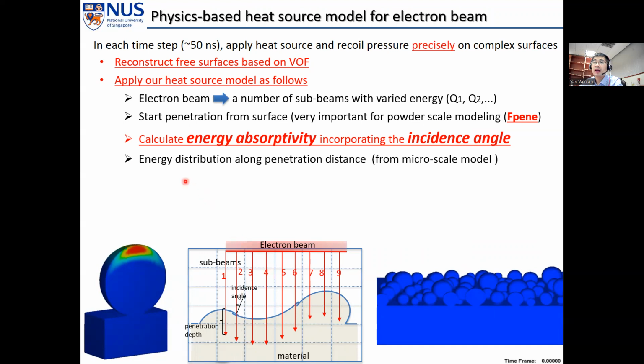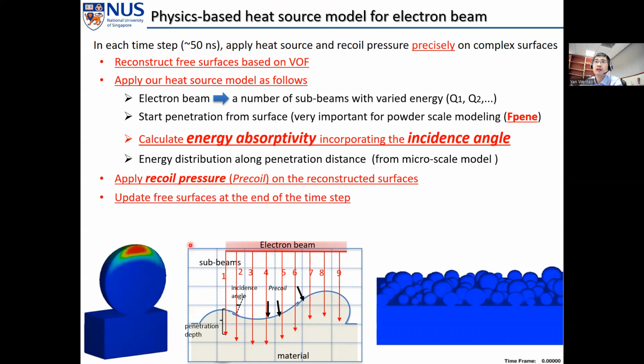And also the energy distribution along the penetration distance is applied based on the micro-scale model. And also we can apply recoil pressure and evaporation on the reconstructed surface, which is temperature dependent and composition dependent. So after this, we update the free surface at the end of each time step. So this is a showcase.